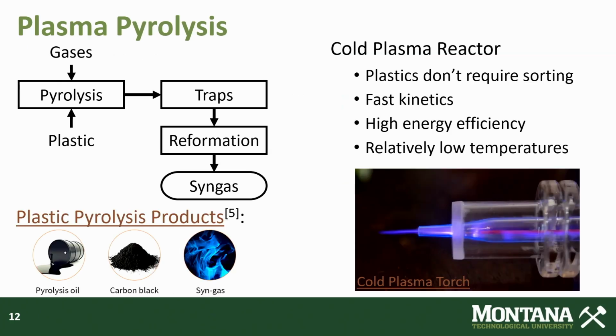So, what are we going to do with the plastic? Well, we're going to pyrolyze it. So we're looking at cold plasma or non-thermal plasma, which has extremely fast kinetics and optimum heat generation with a high degree of energy efficiency. Non-thermal plasmas range from room temperature to over 2500 C compared to thermal plasmas, which are about 6,000 to 8,000 C. And plastics pyrolyze at only 600 to 900 C, so we don't really need to use the thermal plasmas for this process. And the plastic pyrolysis can generate 3 products.